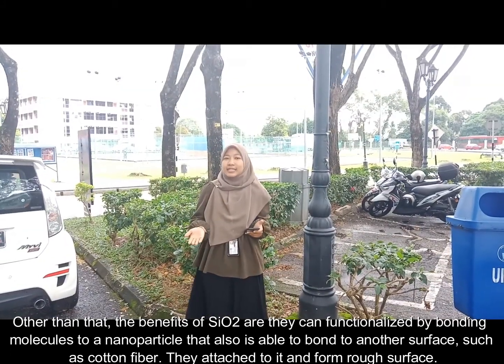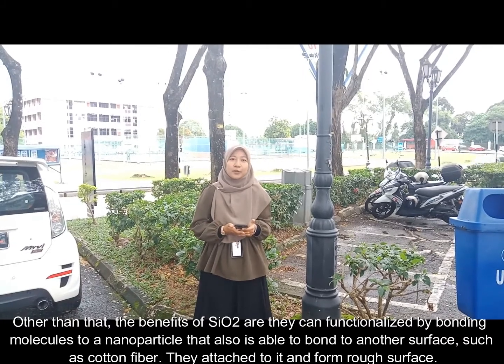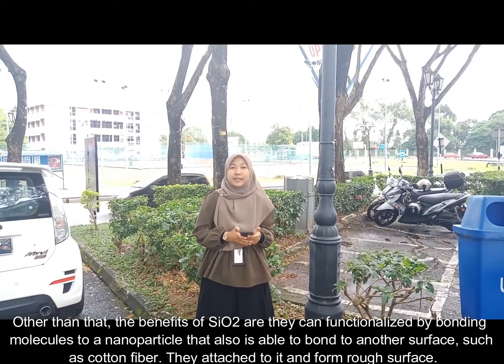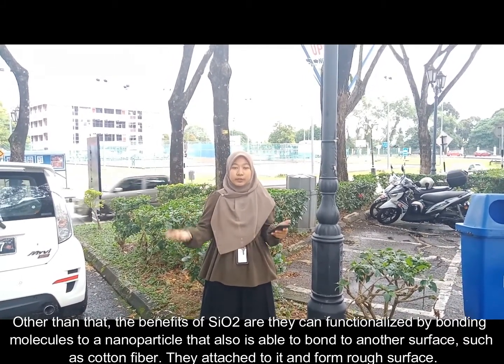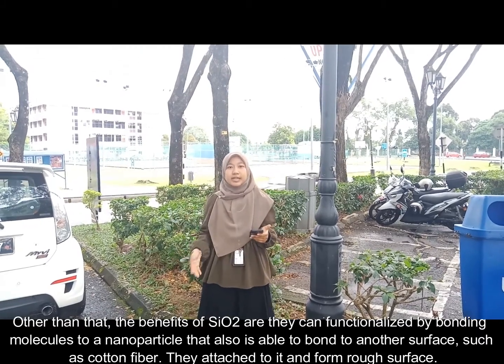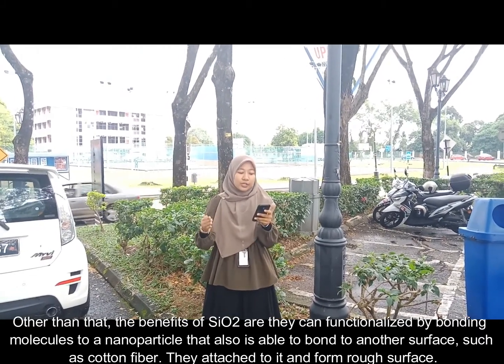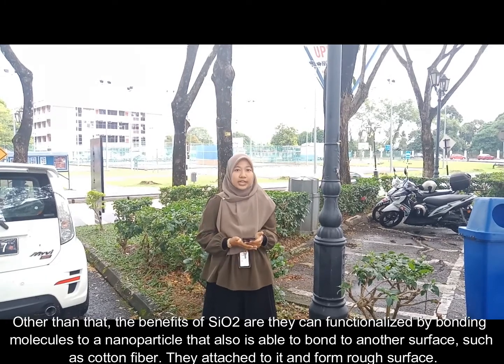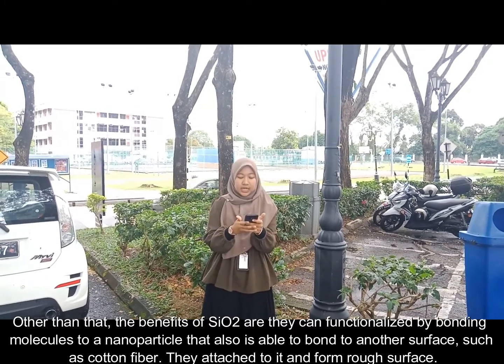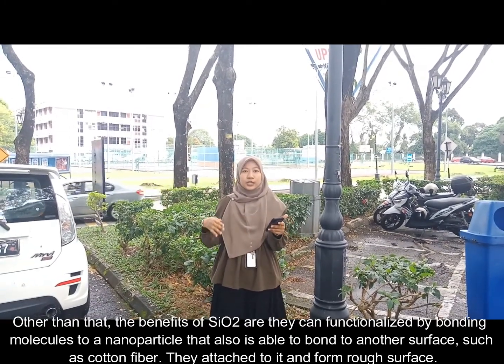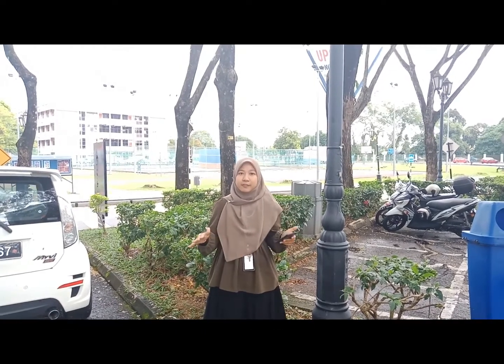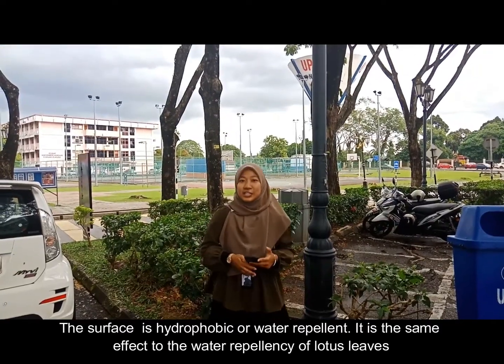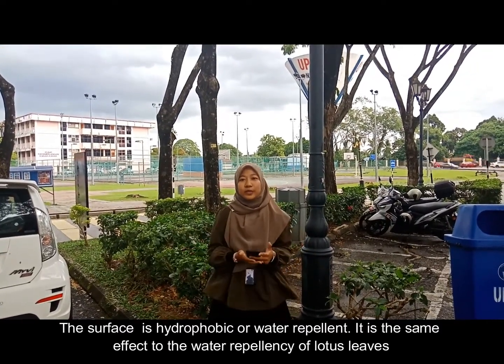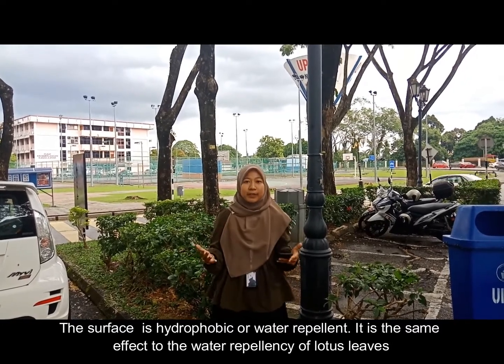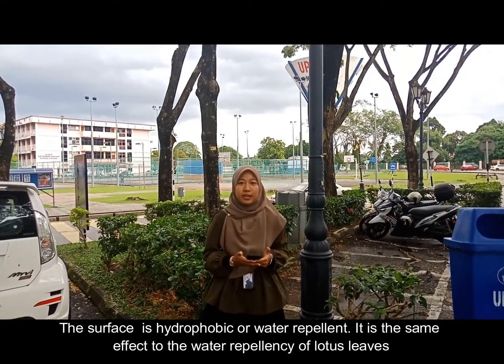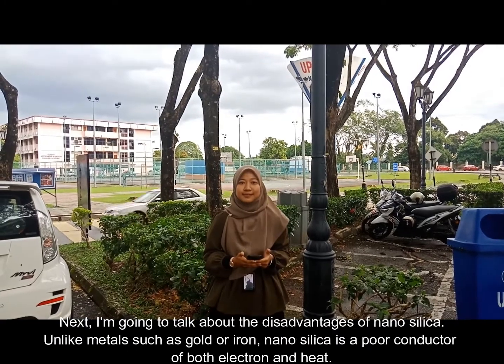Other than that, a benefit of silicon dioxide nanoparticles is that they can be functionalized by bonding to molecules or nanomaterials that also bond to another surface, such as cotton fiber. They attach to the cotton fiber and form a rough surface. The surface is hydrophobic, or water repellent. It is the same water repellency effect as the lotus leaf.